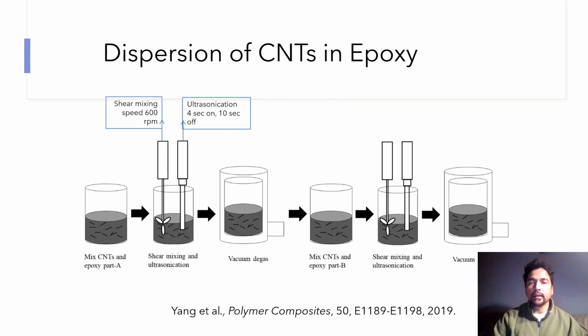Once that is done, it was put in the vacuum chamber to remove any air bubbles induced during this process of mixing. Later, part B of the epoxy, which is the hardener, is mixed in as part of the next step. Then, again, a combination of shear mixing and sonication was performed for a few minutes before it was put in the vacuum chamber again to remove any extra air bubbles induced in the process of mixing. Now this mix is ready to use to make the composite.